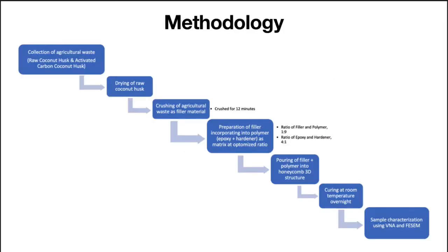The method I used for this research was constructed after reviewing journals. The first one is to collect the agricultural waste, which for my research were the raw coconut husk and activated carbon coconut husk. After that, we have to dry the raw coconut husk in the oven at 60 degrees Celsius overnight. This is to evaporate any excess moisture from water so that it won't bring any malfunction to the crusher in the next process.